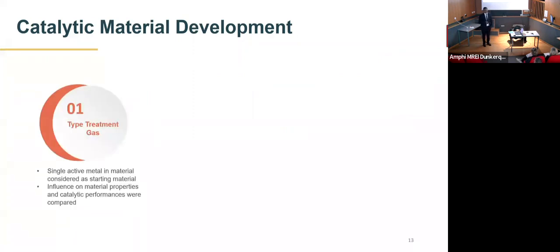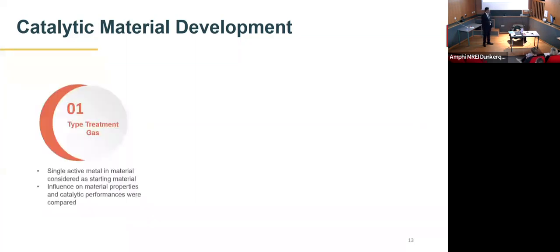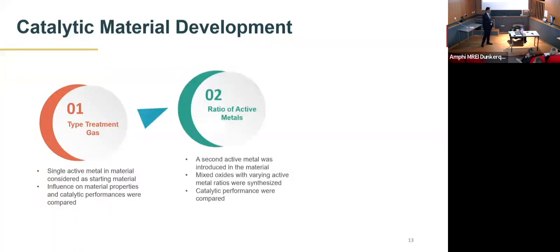So in order to optimize the catalytic material, we followed a linear material optimization technique. The first thing that we optimized was the type of treatment gas. So we used the layered double hydroxide and treated it thermally under different types of gases to form the catalytically active component, and compared the catalytic performance and chose the best type of treatment gas for our application. The second step was to choose the ratio between active metals.